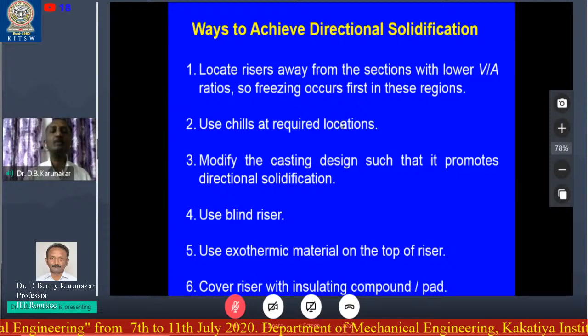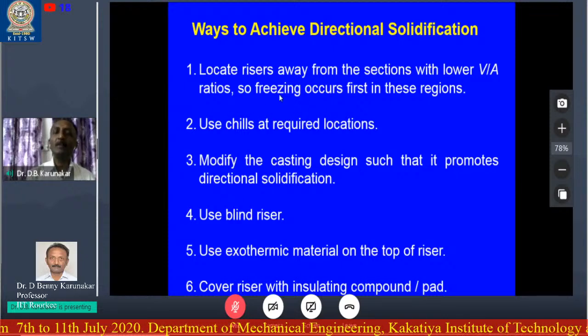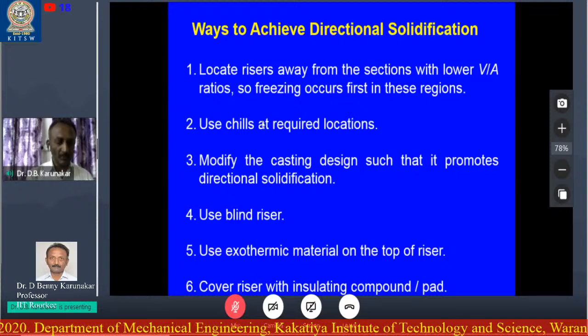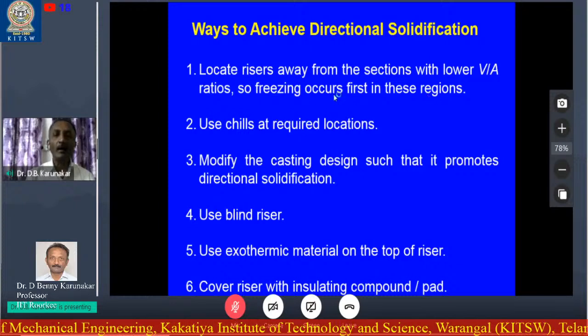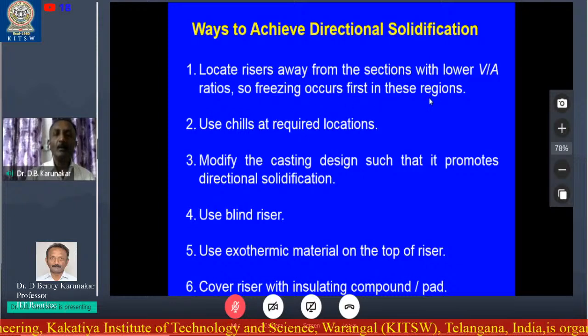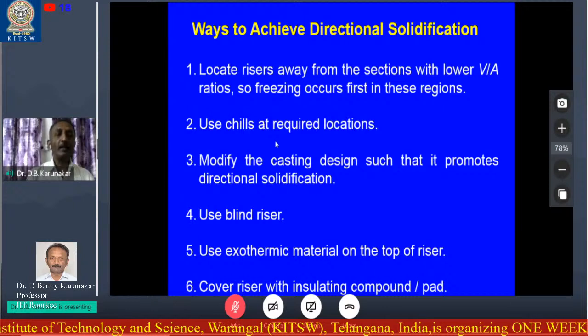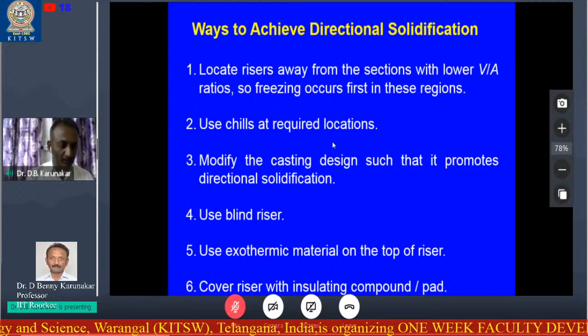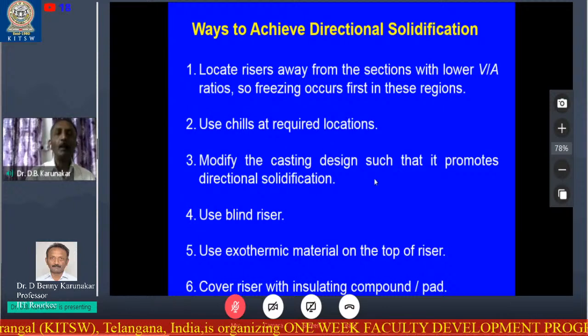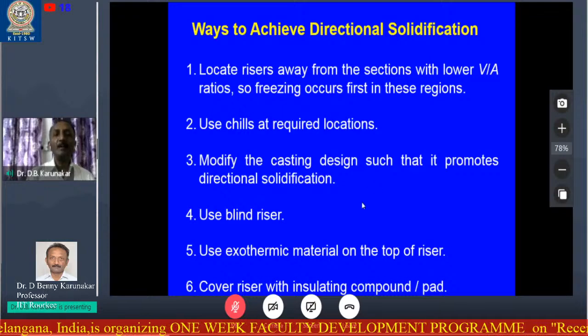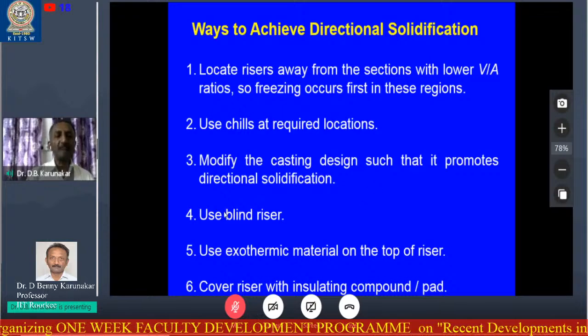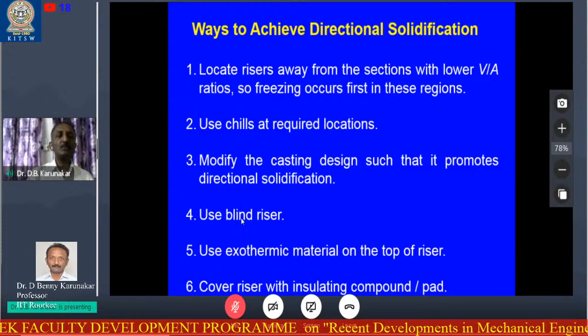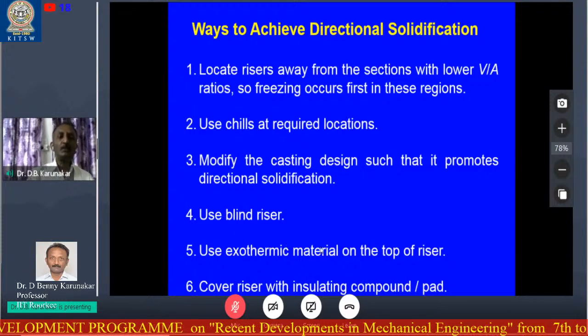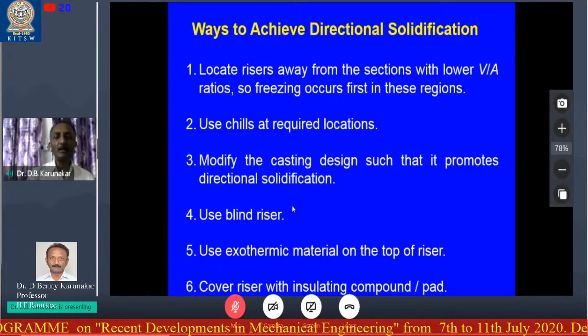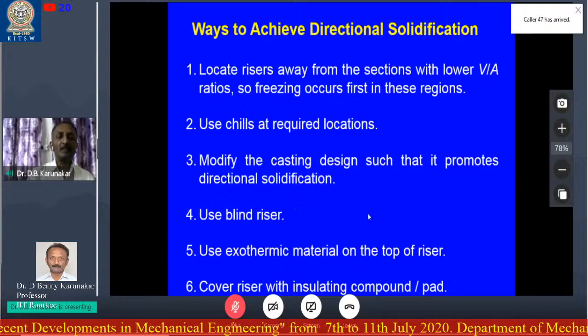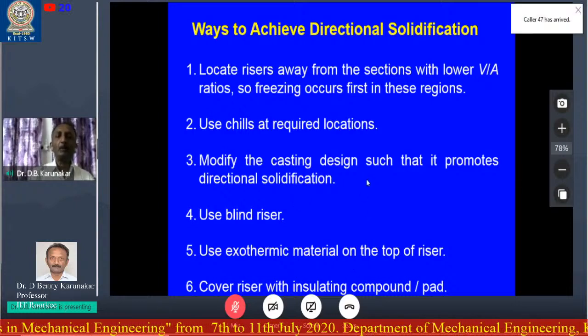Ways to achieve directional solidification: locate risers away from the sections with lower V/A ratios so freezing occurs first in these regions. Next, use chills at required locations. Modify the casting design such that it ensures directional solidification. Next, use the blind riser. Next, use exothermic material on top of the riser. Next, cover the riser with insulating compound or pad.